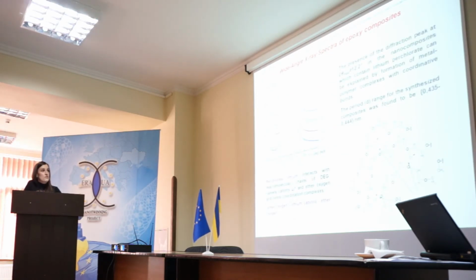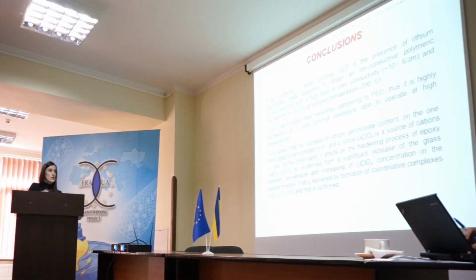The shift of the diffraction peak in the nanocomposites which contain salt can be explained by formation of a metal polymer complex with coordinating bonds. Lithium perchlorate interacts with macromolecular chains of DEG, namely lithium cations and oxygen, and forms a coordinating complex. And conclusions.